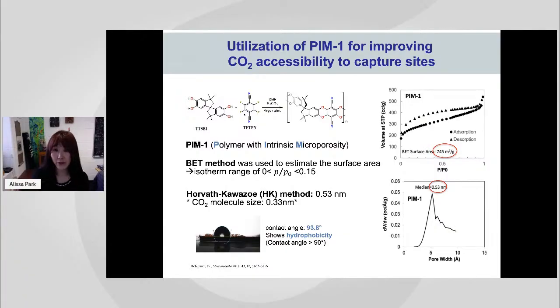All the materials love CO2, and unfortunately also love water, which means that CO2 capture materials compete for the active site with CO2 versus water. More water loading means you need to pay more energy penalty to evaporate that water during the solvent regeneration. So if you can somehow minimize the water uptake during the CO2 capture, that's really favored for overall energetics. By putting on these hydrophobic surfaces, we were hoping that we let CO2 in, but not the water, so that we can be more selective at the surface level.